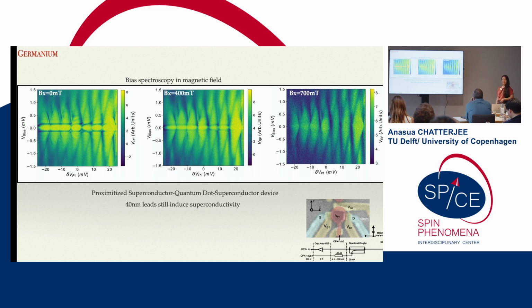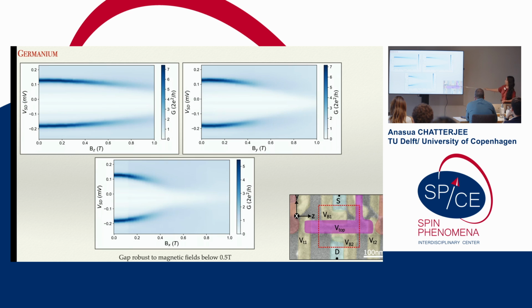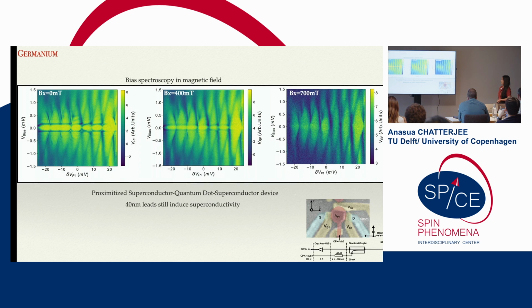Great, that's great. So if you now look at the sensor dot here on the sensor in the side with the RF circuit coupled to it, then you can see that the only superconducting region here is these annealed in source drain leads of about 40-ish nanometer wide. And now you see that if you start tuning the magnetic field, then when it's at 0, you indeed still see a supercurrent, but then you slowly can turn it off by going to 700 millitesla, which is, you know, beyond this in-plane field that you see here.